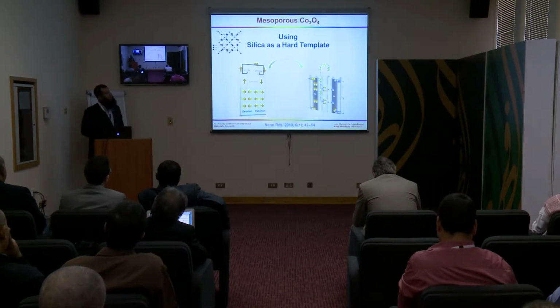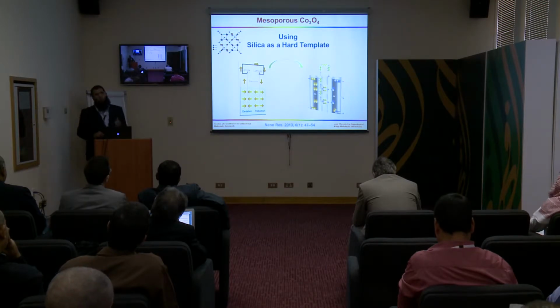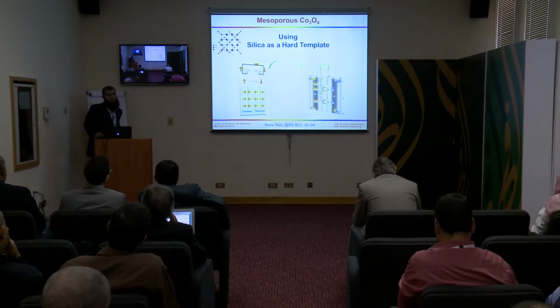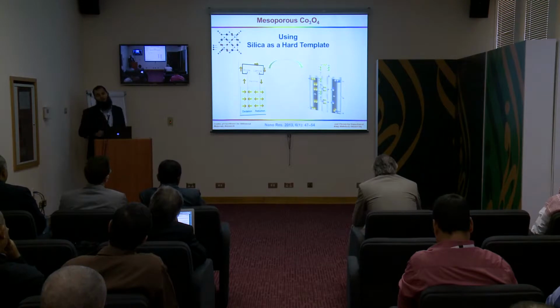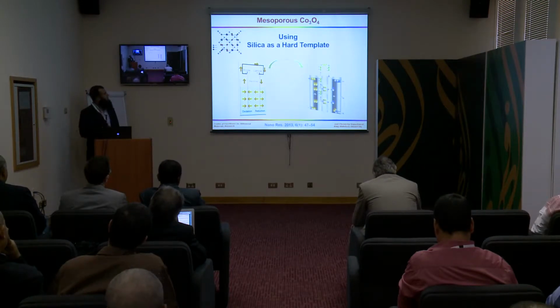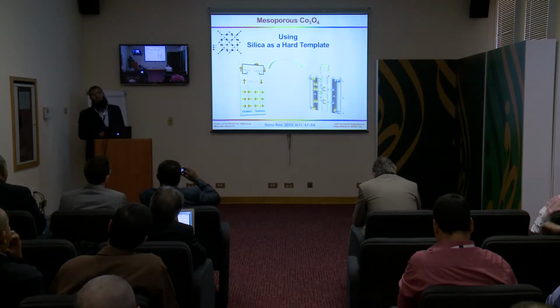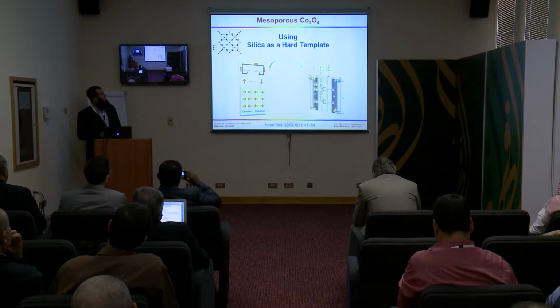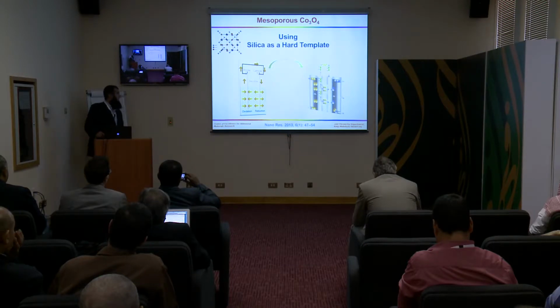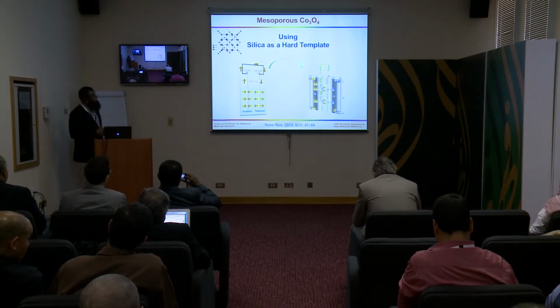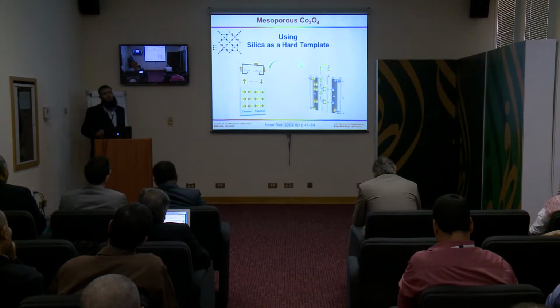For this purpose, the electrolysis method is more promising compared to the other, but in the electrolysis method there is a problem in the sluggish nature of oxygen evolution. The hydrogen production is easy, but the oxygen evolution process is very slow. For that purpose, we need electrocatalysts which can increase the removal of oxygen and quickly split the water. There are many reports about cobalt oxide working as the best electrocatalyst in water splitting.